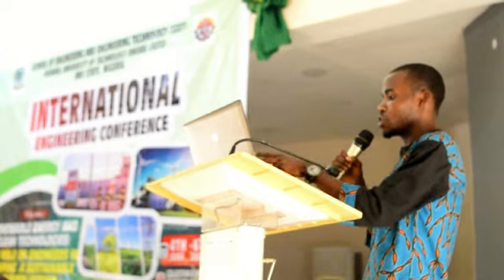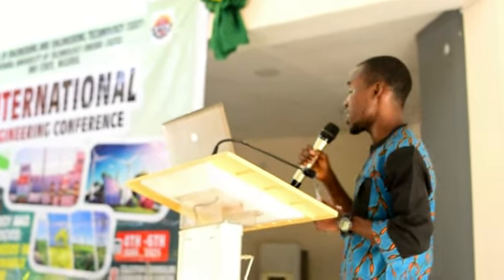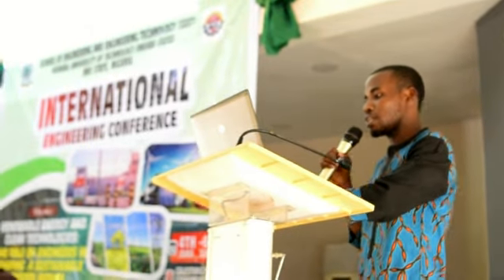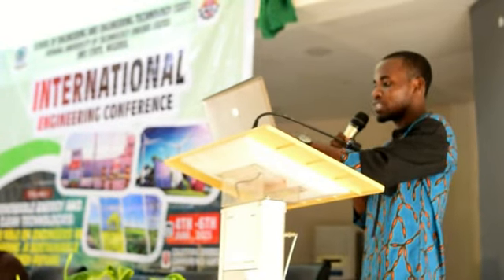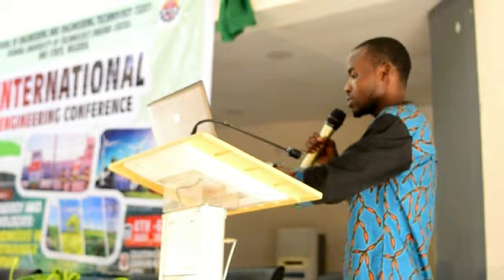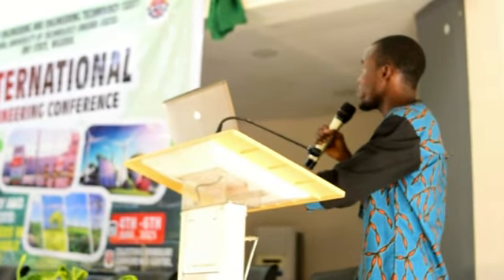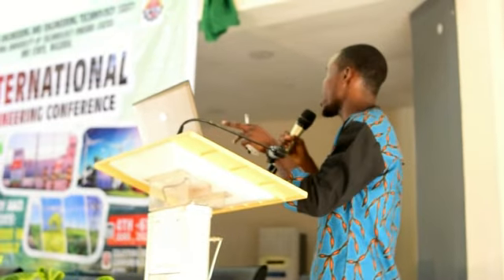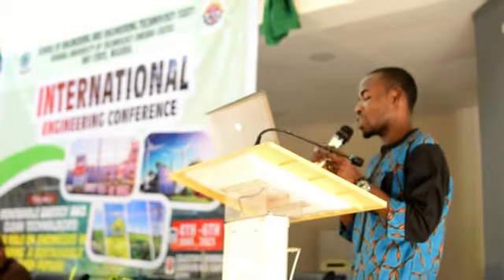And then our equation is the equation obtained using Design Expert, which was used for the RSM analysis. The A, the B, the C, the various variables that we use are represented here as well. And then this is the result of the FTIR analysis that we carried out, the stretching vibration showing the hydrogen present, the peaks at 3,000 to 2,800 per cm, showing the C-H functional group present. And then the implication of these functional groups' presence is that they can adsorb to the metal surface and help form a protective layer that will reduce corrosion on the mild steel.